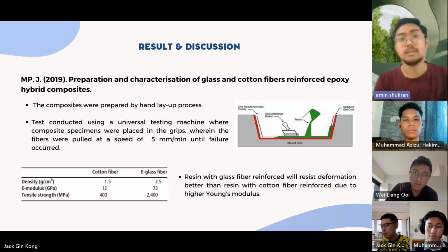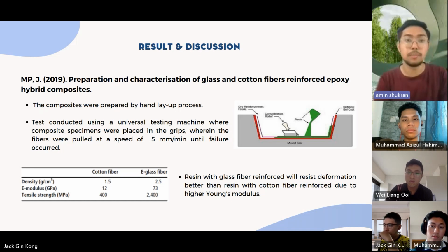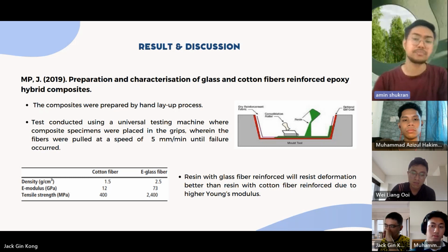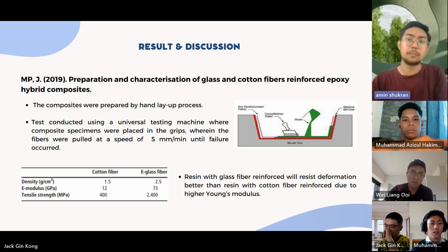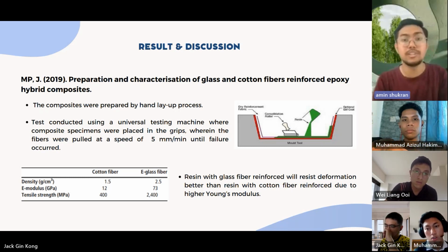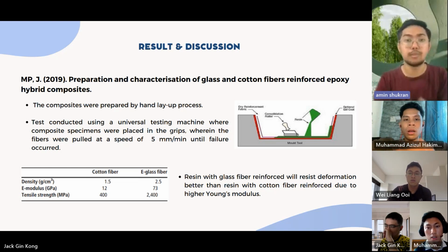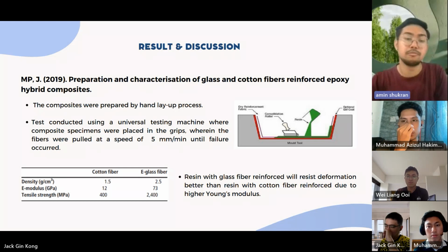Based on the result, glass fiber composite possesses higher tensile strength at 2,400 megapascal compared to cotton fiber at only 400 megapascal. This result showed the comparison without considering the orientation of fibers, but corresponds with mechanical properties like Young's modulus, which indicates that resin with glass fiber reinforcement will resist deformation better than resin with cotton fiber reinforcement due to the higher Young's modulus.